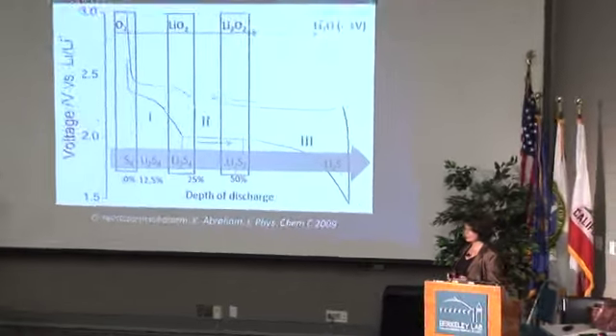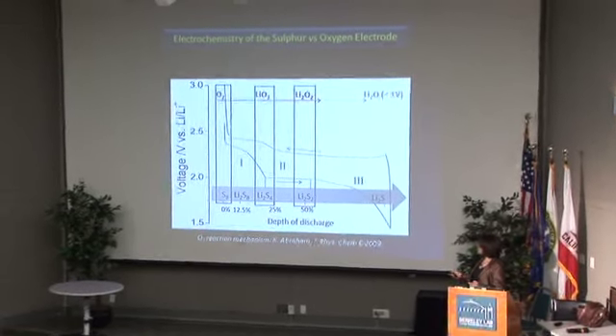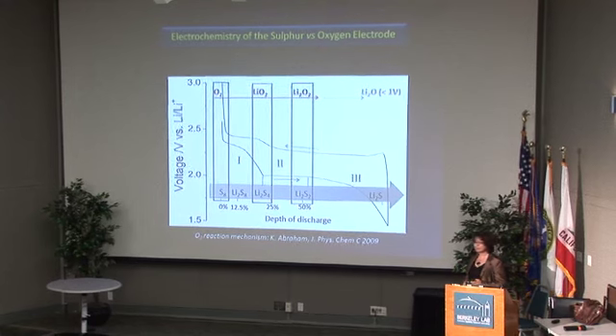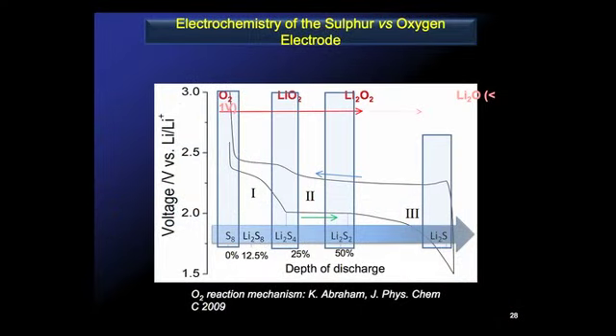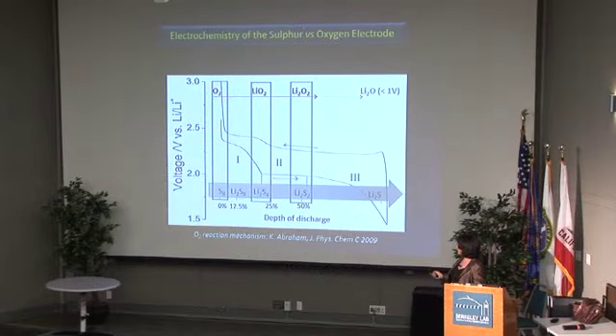In both cases, the question is how to actually make the cell reversible, because especially in the case of lithium-air, the primary cells have been known for a while. In the case of the sulfur, the reversibility is actually pretty easy. In the case of the oxygen cell, it's particularly difficult. There are different problems with each cell, which have prevented either one of them from being commercially implemented. In the case of the sulfur, it is the soluble polysulfides that are the problem. In the case of the lithium-air cell, it is the reactivity of the superoxide and the insolubility of the peroxide that are some of the problems.